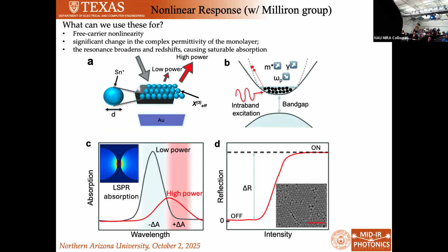Why do we care? Well, one reason we might care is because when you concentrate that much energy into a very small volume, interesting things start to happen. In fact, for these materials, what we were thinking we would see is this really strong electric field confinement, incredibly strong interaction with our free electrons. And when that happens, they get kicked up to these higher energies. They behave differently, right? So they slosh around in a different way, which means the permittivity changes, which means you get out of resonance and you're no longer perfectly absorbing.